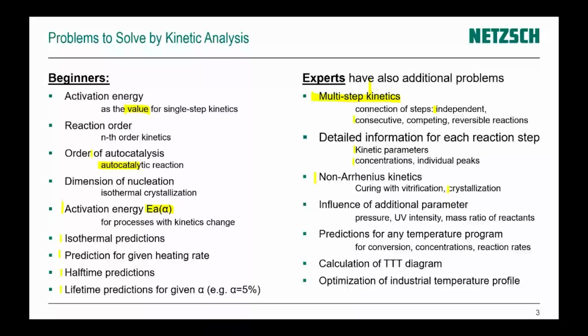For example, crystallization during cooling is also non-Arrhenius kinetics, because we must take into account the glass transition temperature and the melting temperature, and our crystallization happens only in this range. It could be not above the melting point and not below the glass transition temperature. And if we have very fast cooling, then crystallization is not complete, and we must take into account such things.